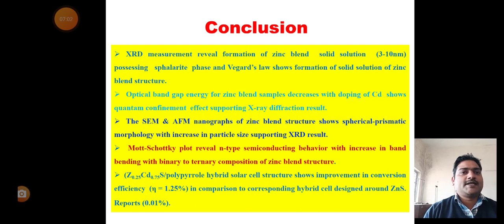Optical band gap energy for zinc blende sample decreases with doping of cadmium, showing quantum confinement effect supporting the X-ray diffraction result. The SEM and AFM nanographs of zinc blende structure show spherical prismatic morphology with increase in particle size supporting the XRD result. Mott-Schottky plot reveals n-type semiconducting behavior with increasing band bending from binary to ternary composition of zinc blende structure.